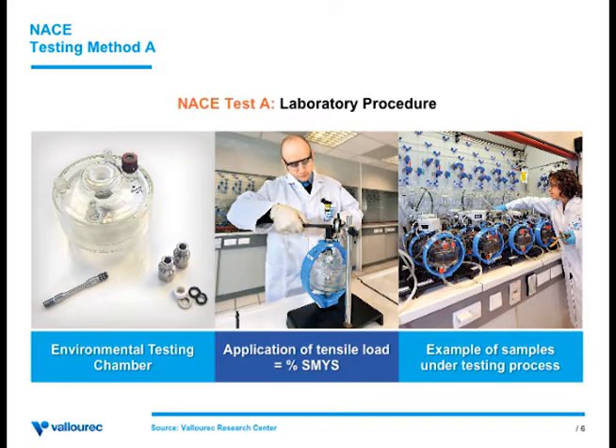This is an example. There are several pictures displayed on the PowerPoint, which show you the testing. You can see the sample is machined. It looks like a tensile test sample, and that would be placed into a loading cell, and then we will apply a load that would always be a percentage of the specified minimum yield strength of the steel. For example, if you have a grade with a 105 KSI minimum yield strength, we would apply a load of 70, 80, 85%, depending on the requirements. Vallourec has several labs where we can do the testing in-house, either for research purposes or for actual orders. But there are a lot of certified labs around the world that can perform this kind of testing.